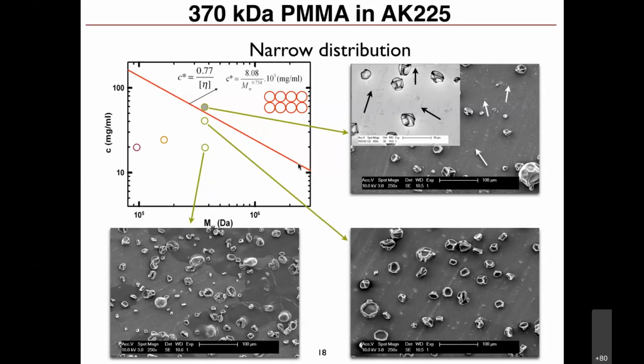They're touching, so it becomes something like this. They're touching each other. Then it's called overlap concentration. So they're overlapping with one another. If they're far apart from one another, then it's basically dilute. They know that if you're above this, you'll start forming fibers. If you're below this, you're not going to get fibers. So we were below this, we don't see any fibers. We are below here, we don't see any fibers. And we just cross the line, we barely start seeing the fibers here.